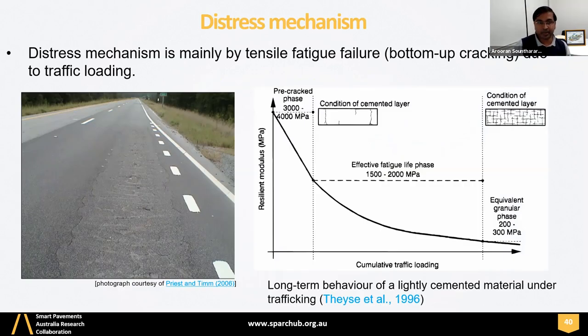What is the common distress mechanism of this pavement? As I indicated in the stress strain analysis, this type of pavement is considered in between semi-rigid and rigid, and the failure mechanism is fatigue due to its pavement response under traffic loading. It is bending. So bottom-up fatigue cracking is commonly referred to as the failure mechanism for this type of material. For those who don't know, fatigue can be broadly defined as a progressive and localized structural deterioration that occurs when cyclic or repetitive loading is applied. This pavement bends repetitively under traffic loading, therefore the cracks at the bottom propagate to the top as tensile fatigue.